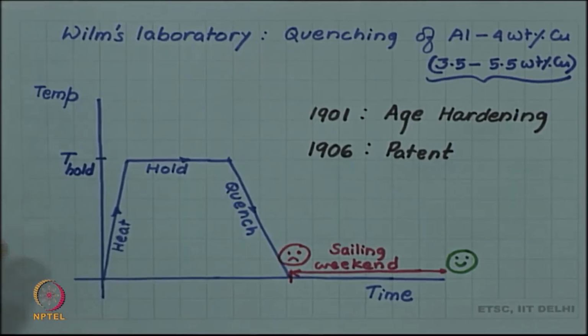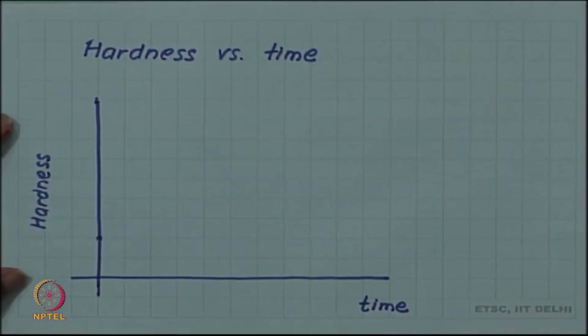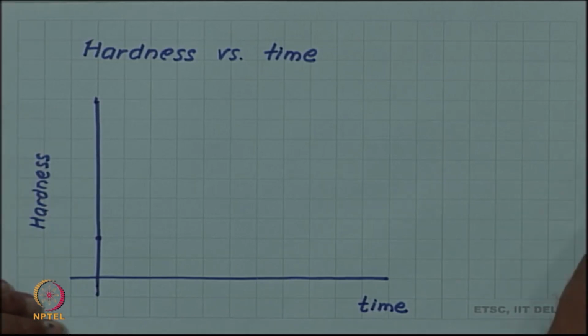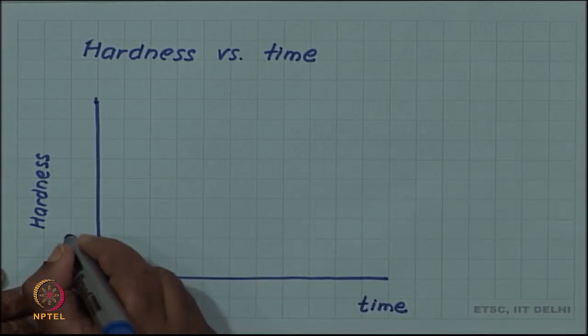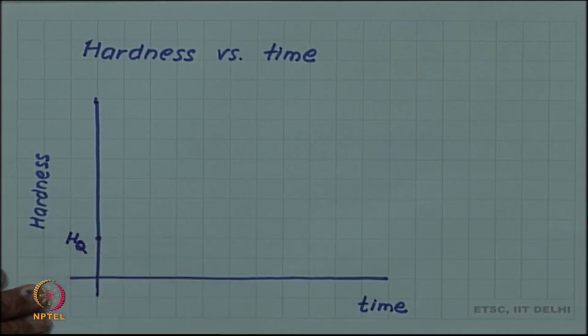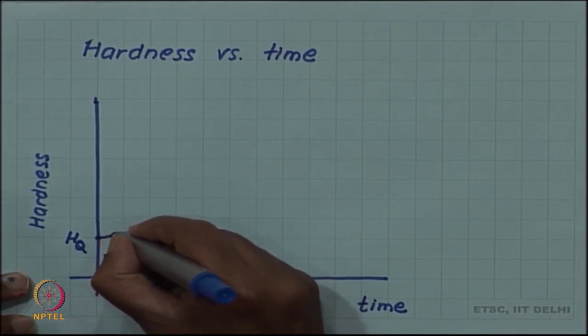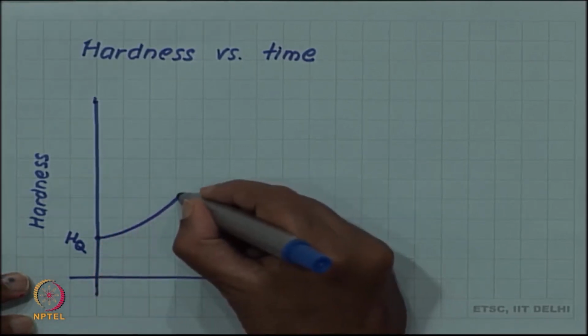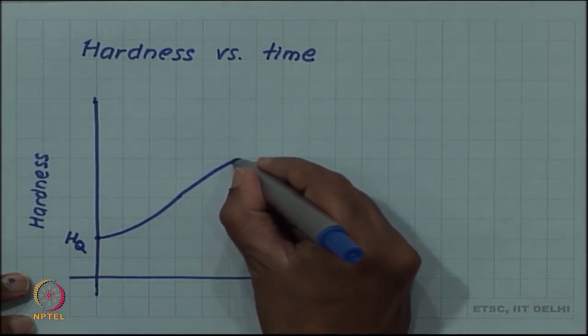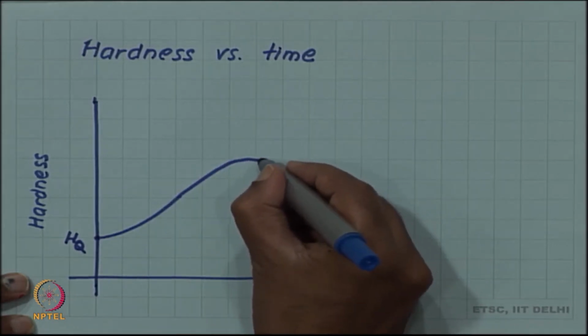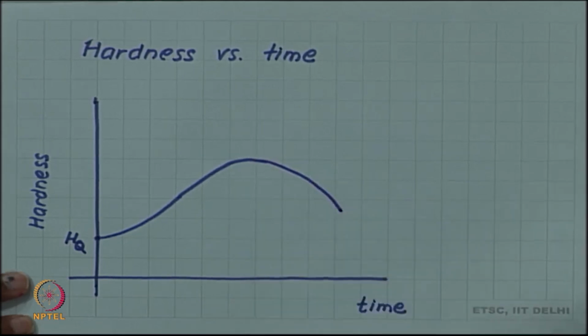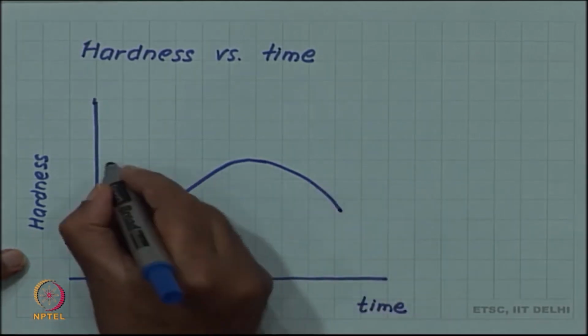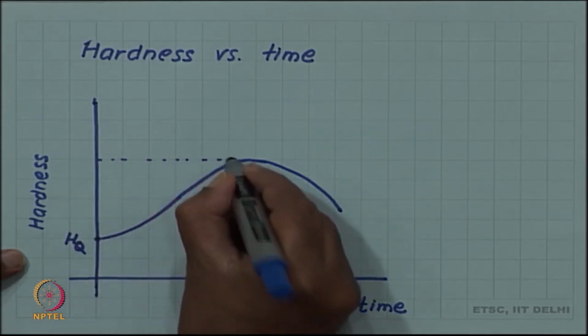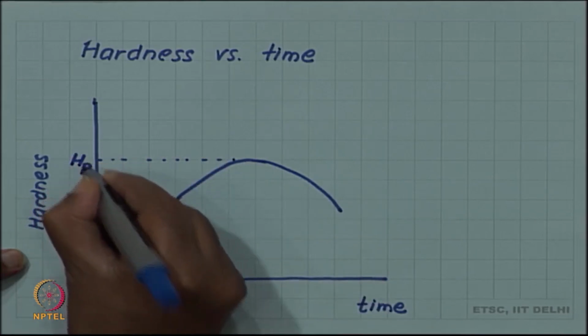So, let us look at what he found on aging, or how does the hardness change as a function of time. So, after quenching there is a hardness value and let us call that HQ, hardness in the quenched state, and then as time passes the hardness starts increasing and starts going up, but then at some point it reaches a peak and then decreases. Let us call this hardness the peak hardness.